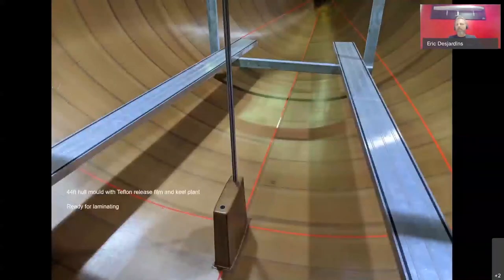This is what the female mold looks like when it's finished. So you can see we have inside the mold a center line. We've got the station I mentioned before, which is our thwartship reference. And we've got our waterline, which is our horizontal plane. This tape will stay in the mold when we start laminating. So when we release the hull, we have this reference pretty much scribed into the composite material. So we can then assemble the boat very accurately using those measurements.